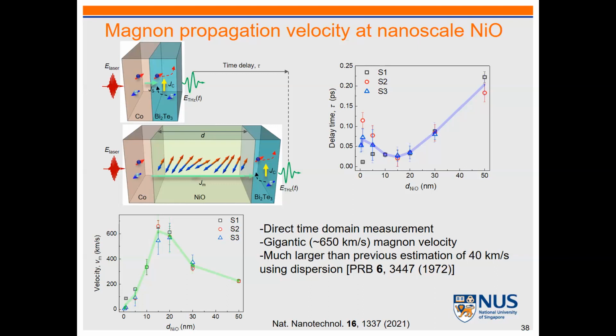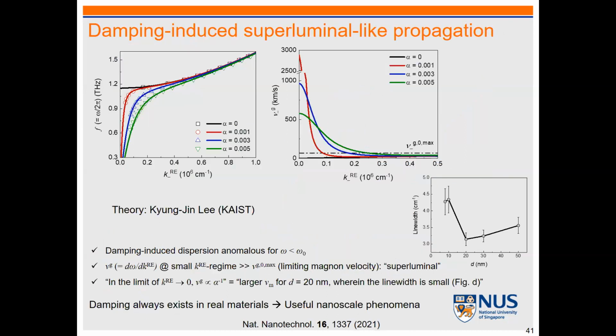So what we are measuring is kind of a nanoscale phenomenon, which can be very different from the bulk phenomenon. And how do we understand this? So we had a collaboration with Kyung-Jin Lee at KAIST, and once you have damping of the real materials, basically your dispersion is distorted in the small k vector regime, and depending on this damping parameter, you can see the dispersion can be even more distorted. Basically, the derivative of this is connected with the velocity in this frequency and k vector. So basically, you can have very large velocity in this region. So that is our understanding. And in real material, we always have damping. So probably it's useful in nanoscale devices.